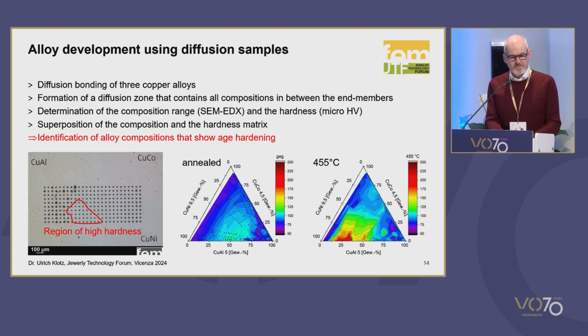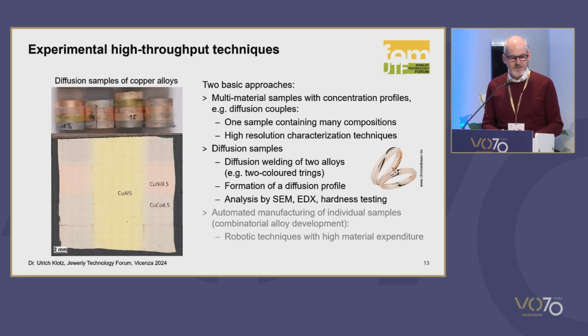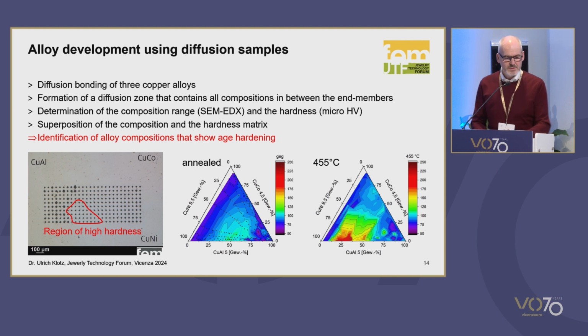So you see the 3 different alloys from this example. You can see them here in 3 corners of this image. And the points that you're seeing here are hardness indents. And you can already see by eye that in some regions the hardness indents are larger. This means the alloy is softer, and in some regions they're smaller, so the alloys there are harder. Now we have to match the composition of the alloys with their hardness. And there are these 2 triangle diagrams.